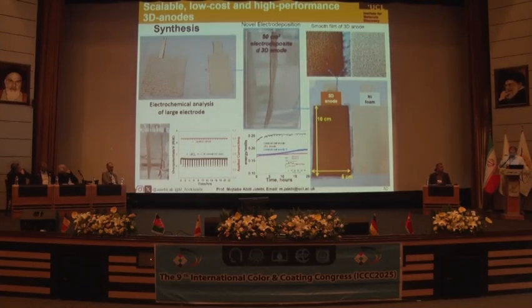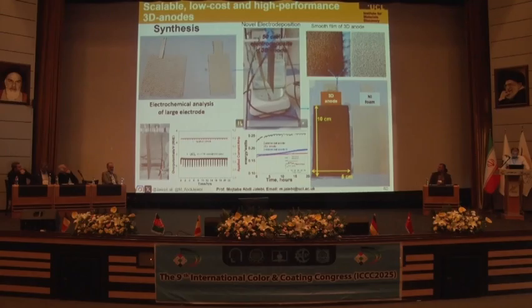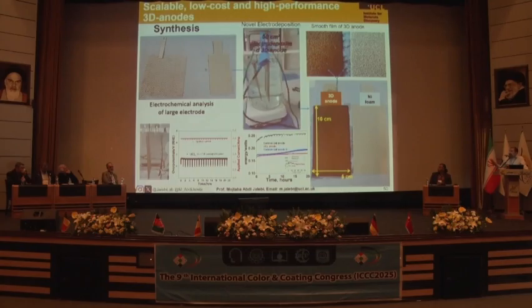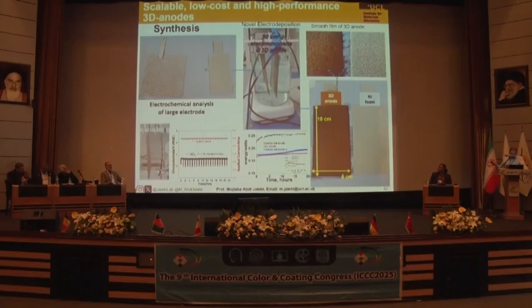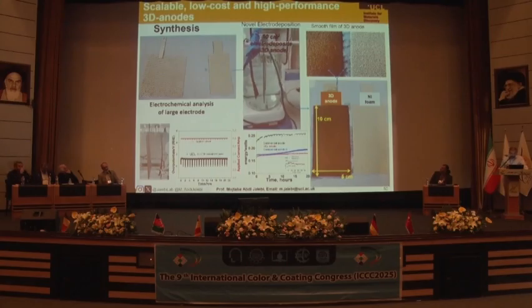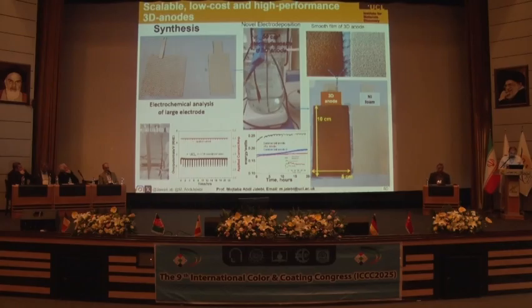You can see that there's a video here, I'll try to play it. This is electrochemical electrode deposition of the electrodes that we are developing. So basically it's 50 square centimeter, and obviously we are still in the lab here. And you can see that the final product is also over here, 50 square centimeter. We are going even higher at the moment. And in terms of performance, you can see that it's very stable compared to other commercial candidates, like iridium oxide, for instance.